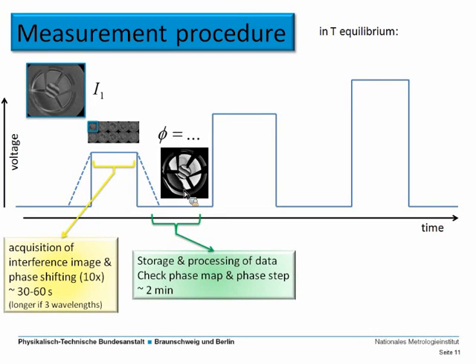And then when we switch the voltage off, we use the time while it is off to store and process the data. So, just calculate the phase map, check whether the phase stepping worked perfectly and everything. This is just an example of what the phase map looks like, which is calculated from those interference images. This takes about 2 minutes at the moment. And then we repeat this for every voltage step we are looking at.